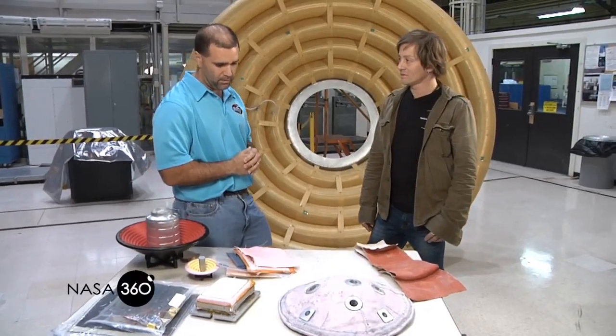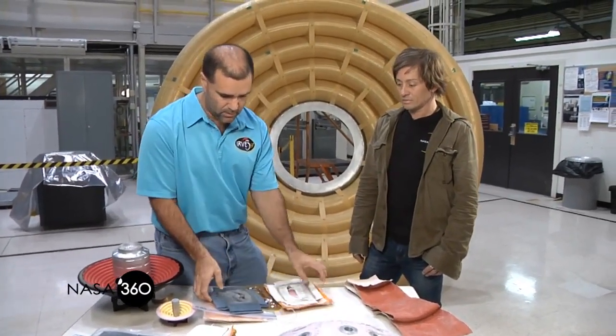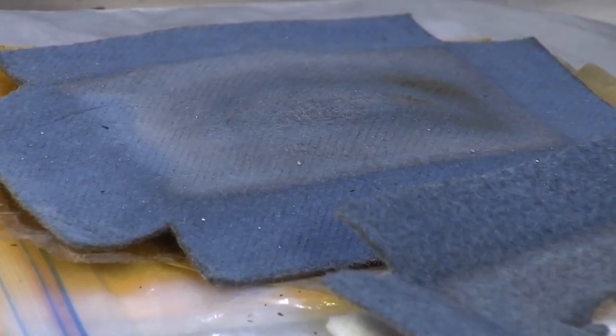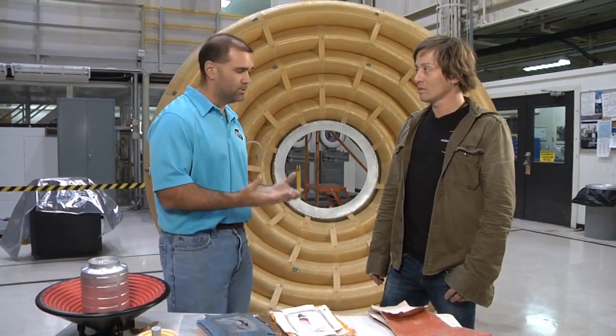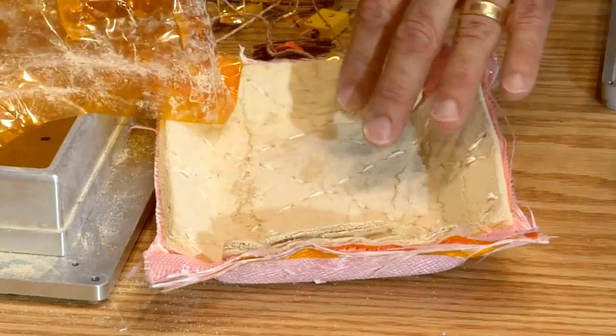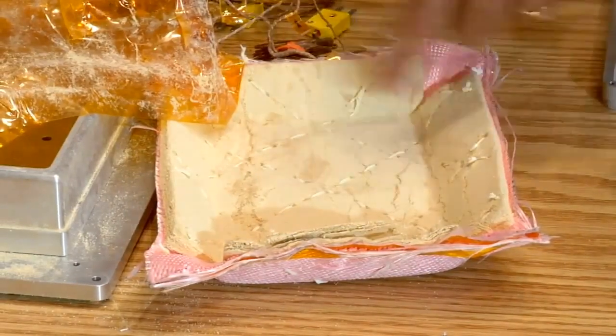And then the underlying ply that we have right now for IRVE-3 is a material called Pyrogel 3350. This is an aerogel. Aerogel is a very, very low density glass that's been impregnated into a fibrous bat. It's somewhat flexible, and then behind that, an assembly of polyimide film with a Kevlar scrim embedded in between it to give it a little extra strength.